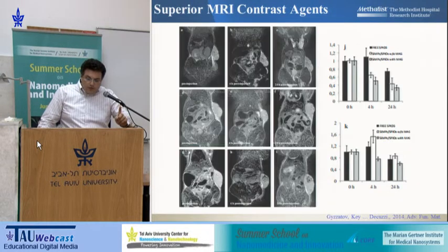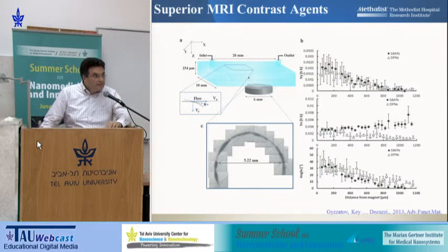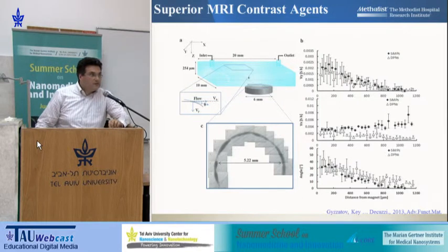Now, I want to show just 3 slides, if I can. We are all familiar with magnetic drug targeting and magnetic guidance. It is not a new concept, but I think that by confining iron oxide nanoparticles into larger vectors like the mesoporous silicon particles and Discoidal Polymeric Nanoconstruct that we are developing, you can really get the most out of this approach. Why? Because magnetic forces are volume forces, and volume forces do not like nanotechnology. We learned it from the previous speaker. They scale with the size at the cube, and of course all the surface forces, they scale with the size to the power 2. And so the only way to increase the efficiency of magnetic drug targeting is to confine multiple SPIOs within one single particle.